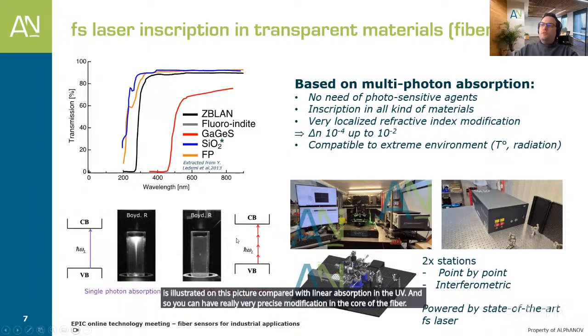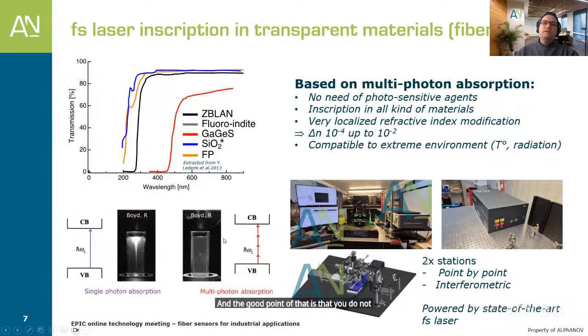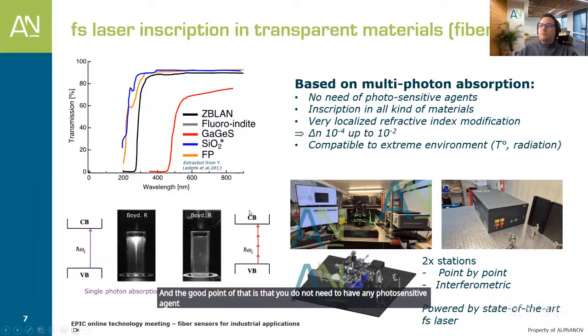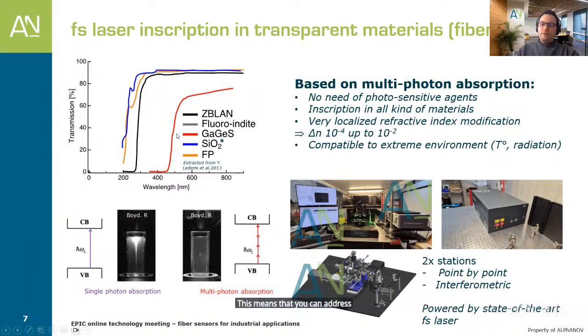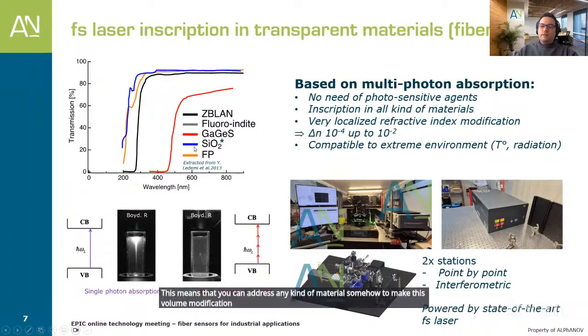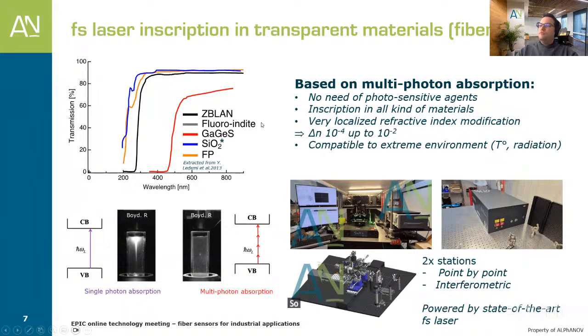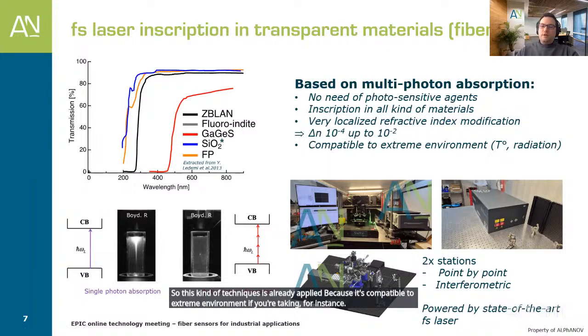And the good point of that is that you do not need any photosensitive agent to UV-sensitize the fiber. This means that you can address any kind of material to make this volume modification and to write this refractive index change. So this kind of technique is already applied because it's compatible with extreme environments if you're taking, for instance, silica glass, and because the kind of FBG you can write inside the fiber will not be too sensitive to temperature or even radiation, because you can really write into pure materials.